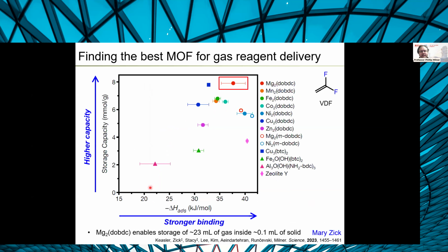And what we compared was their storage capacity for the gas, which we want to maximize to minimize the amount of MOF we need to deliver the gas. And also the binding strength, the enthalpy of adsorption, which we want to maximize so the gas doesn't just leak out of the MOF before we want to actually use it in a transformation. And she found that this magnesium-based MOF, magnesium DOBDC, also called magnesium MOF-74, probably many of you are familiar with it, was actually the best in terms of binding vinylidene fluoride with a high capacity and relatively strong binding.